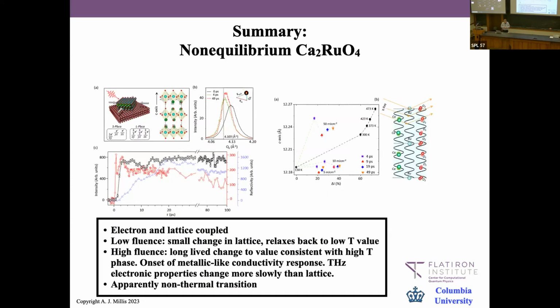So this is just to summarize: you have a low fluence, things just relax back to their equilibrium state. At a high fluence, you get a long-lived change. The long time state is apparently non-thermal in the sense I gave, and the electronic properties change more slowly than the lattice.